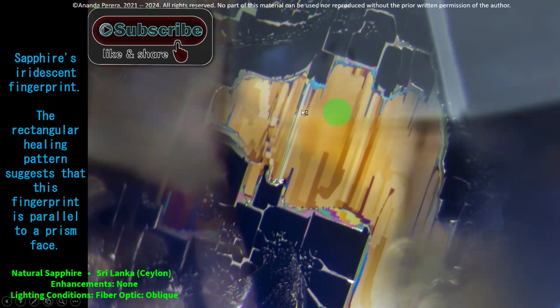Then this is the sapphire's iridescent fingerprint. Here iridescent colors are showing. The rectangular healing pattern suggests that this fingerprint is parallel to the prism face, parallel to the C-axis. The lighting condition here is fiber optic oblique.